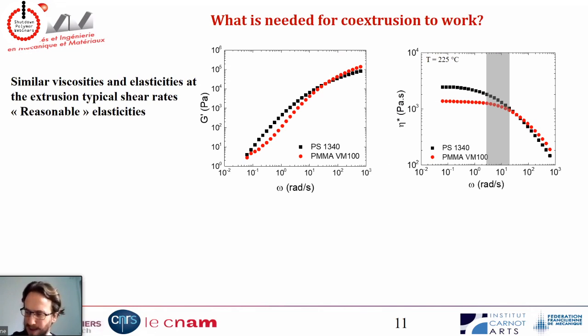So now I'm moving back. I told you some generalities about blends, and I'm going back to coextrusion. To make coextrusion work, you have to think about the rheology a little bit, because in the barrel with the screw, you have some shear applied to the material, and it's in the melt. So you have to think about the rheological properties of your polymer. And because in the die the two polymers connect, the rheological properties of the two polymers have to be connected. Actually, for it to work, you have to make the rheological properties quite similar for the two polymers at the extrusion temperature and at the shear rates that are typical for coextrusion.